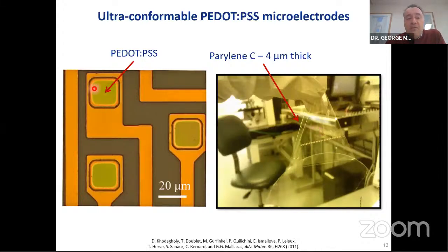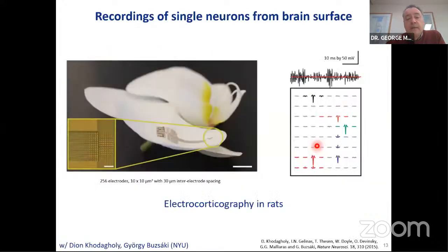This is shown here, where we microfabricated PEDOT:PSS electrodes to make them the same dimensions as the soma of neurons in the brain, same order of magnitude. And we integrated those with flexible, thin plastic substrates so that they can follow the curvature of the surface of the brain and make good contact. So as you see this electrode, this is a denser array that has 10 by 10 micron square electrodes. And you see that it conforms nicely to the shape of an orchid leaf, showing radii of curvature that are appropriate for sitting on the brain. And then when this was placed on the cortex of a rat, we were able to measure this spiking activity that corresponds to single neurons being picked up by different electrodes.